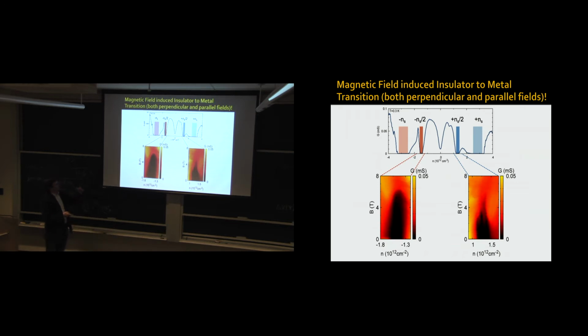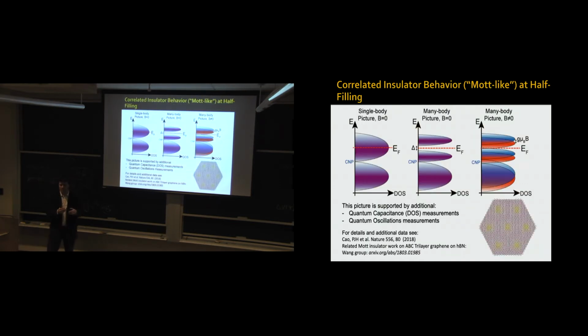So basically, after a number of other experiments and so on, and to cut the story short because I want to show you the superconductivity data, what we came up with was the following. There is this set of flat bands in graphene—this is the charge neutrality point. When we tune our Fermi energy such that we have half as many electrons as we can put in this conduction band, or half as many holes, interactions between the electrons lead to a correlated gap that turns your system into an insulator. This correlated gap is probably made out of singlet states. When you apply a Zeeman magnetic field, you polarize those bands so that you close the gap, and now they have band overlap, so you can start conducting.